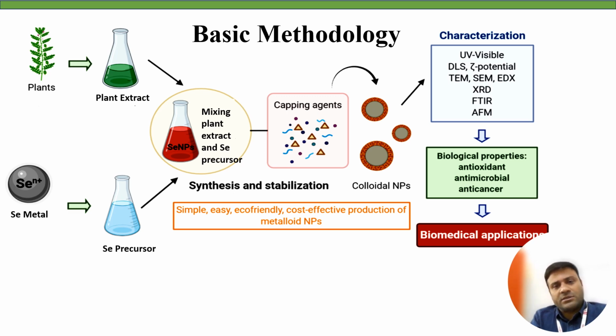This mixture was heated to a controlled temperature between 60 and 90 degrees centigrade while stirring continuously for a defined duration. A noticeable change of color was observed from colorless to red or orange during the reaction. It indicates the formation of selenium nanoparticles.